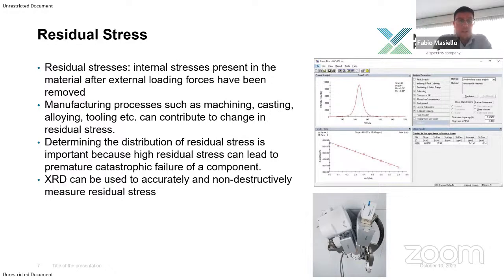Determining the distribution of stress is important, because if there is a high residual stress, that can also, in certain parts, lead to premature catastrophic failure. XRD is one of the tools that are used to accurately and non-destructively measure residual stress. And on the right side, you see, for example, a screenshot of software that can measure stress.